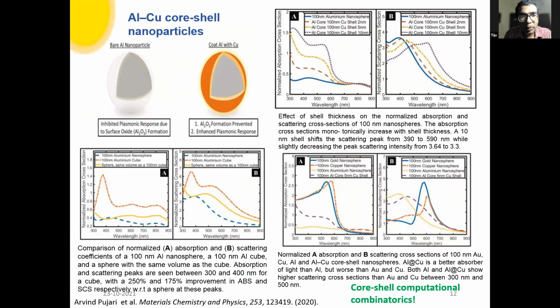So furthermore, we have been looking at core shell nanoparticles, and we call it core shell computational combinatorics, wherein we have demonstrated in particular that these core shell particles, if that is aluminum when covered with copper in particular, it turns out that, number one, chemically you can expect it to be more stable and not having an oxide like the one that in particular you would be worried about in the context of aluminum nanoparticles standalone. Aluminum nanoparticles standalone do not survive in water, but aluminum coated with copper, they do survive in water, and they stay pretty long even in atmosphere.